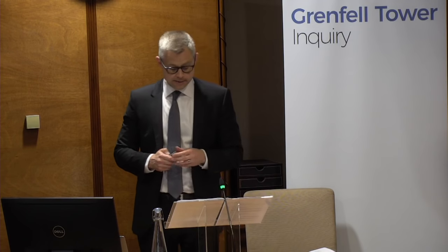The heat release rate is therefore important for evaluating the fire hazard associated with an object. This is because it determines the energy released from a material that is available to be transferred back to the fuel, thinking again about my match, thus creating a feedback loop which may sustain the flaming. Materials with a high heat release rate therefore typically result in more rapid fire growth and/or fire spread. And so the growth and spread of fire are obviously of fundamental importance to this inquiry.